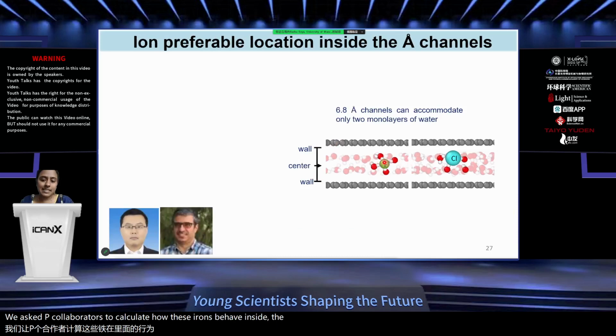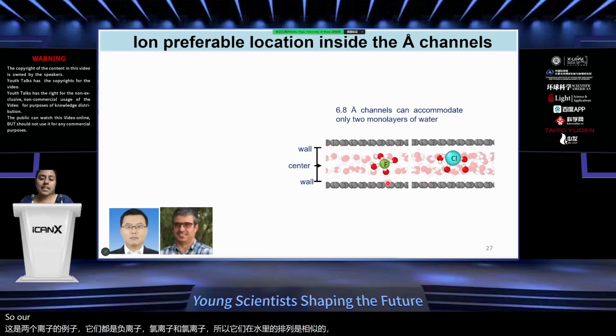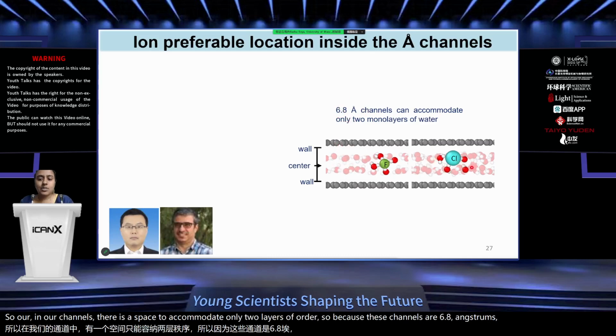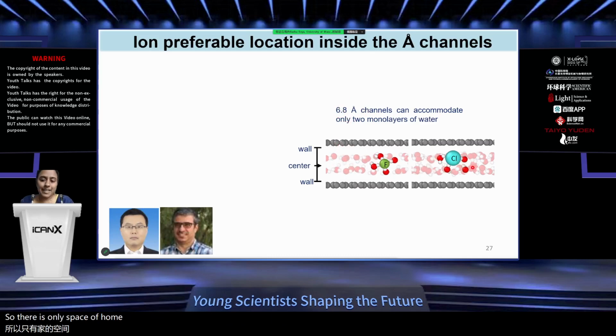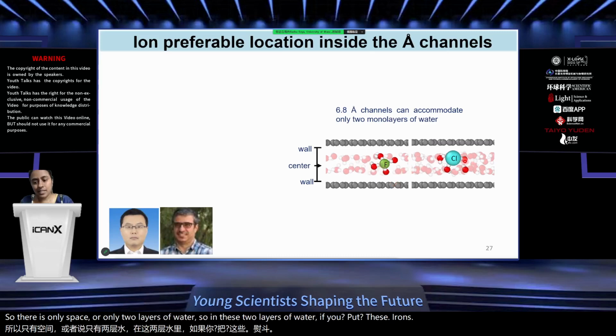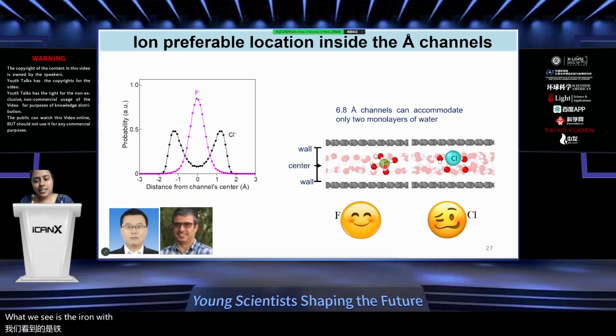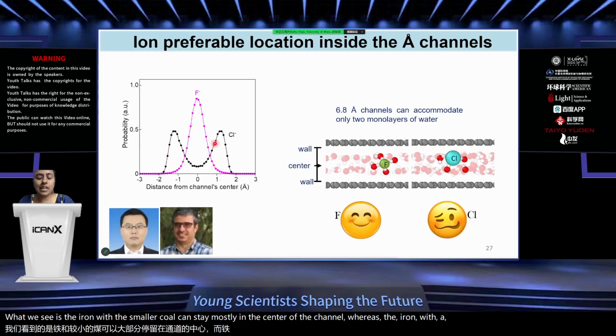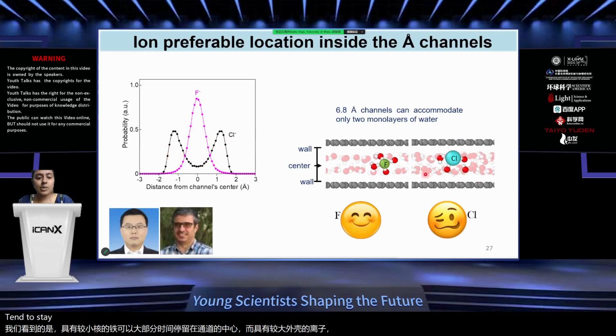To understand this further, we asked our theory collaborators to calculate how these ions behave inside the channels. This is an example of two ions, both negative ions, fluoride and chloride. So their water arrangement is similar. In our channels, because they are 6.8 angstroms, there is space to accommodate only 2 layers of water. In these 2 layers of water, the ion with the smaller core can stay mostly in the center of the channel, whereas the ion with the larger core tends to stay mostly near the walls.